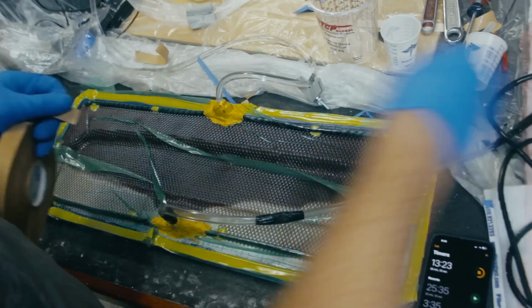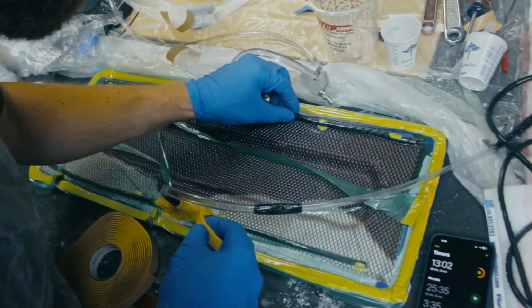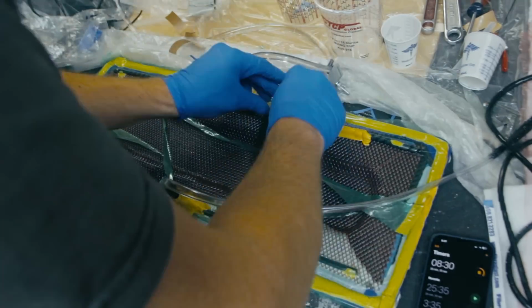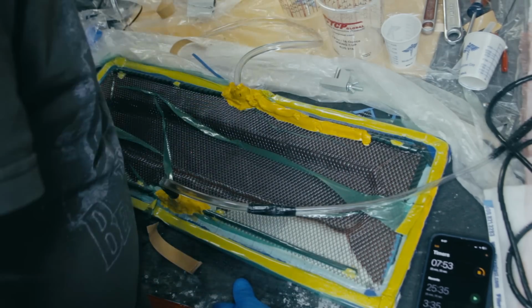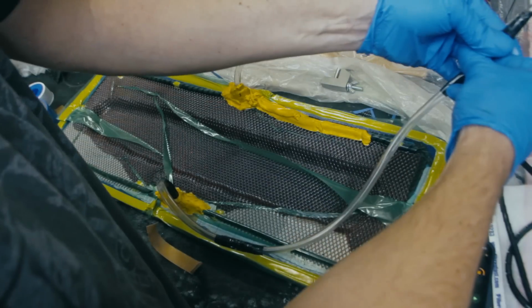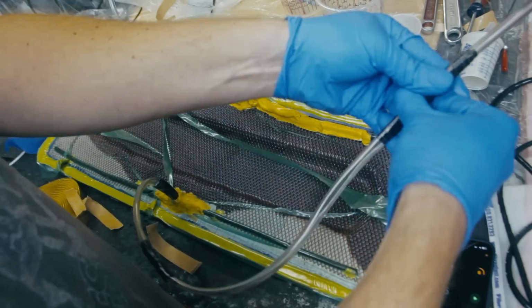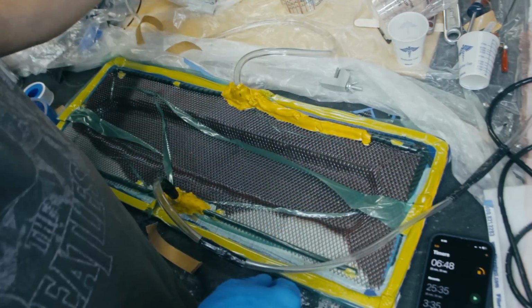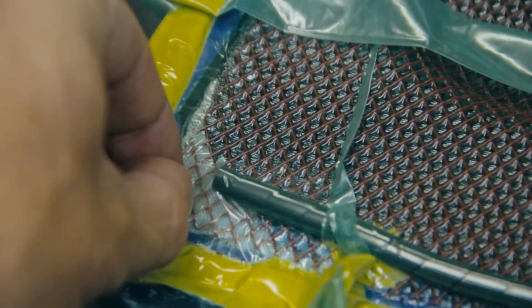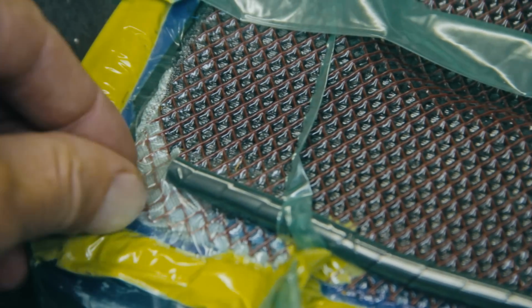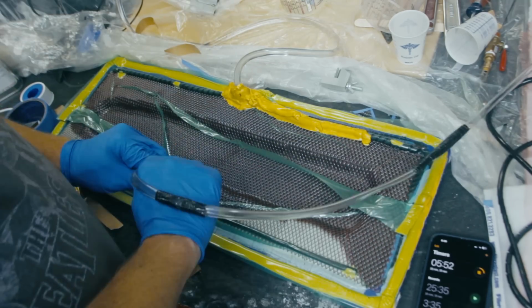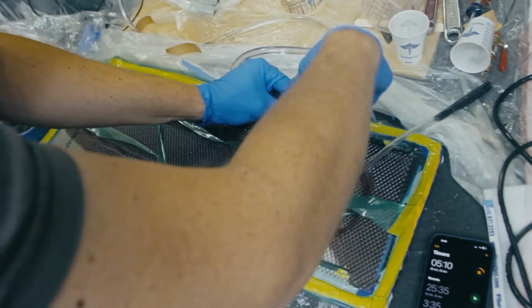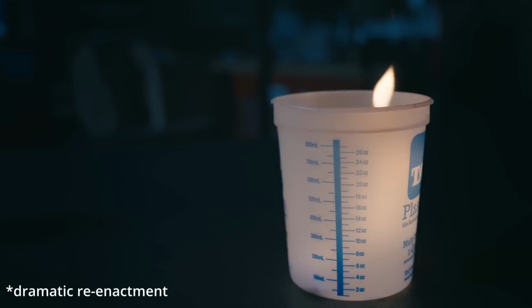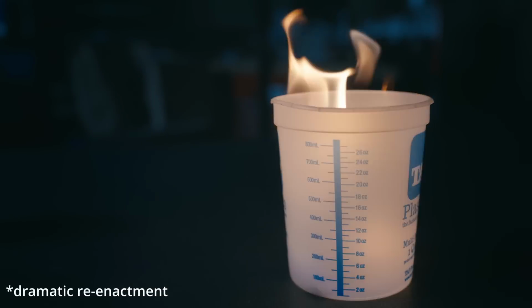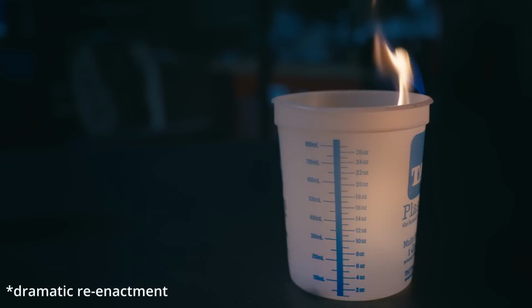So I paused the infusion for a moment by clamping the resin feed line, and did my best to seal the, let's be honest, numerous leaks. And then I reopened the taps to allow the resin to flow again. But nothing seemed to be flowing. The resin had already reached the vacuum line and started to plug it up. So vacuum was no longer getting to the part. I did my best to mitigate this, and got some more resin to flow through the part. But it was about then that my pot of resin began to smoke. So yeah, this infusion is over.